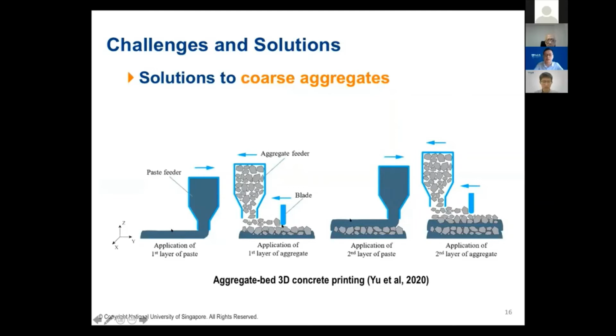Then we put another layer of cement paste. Then the cement paste could diffuse into the pores to fill all the voids in the aggregates. Then we put another layer of aggregate. Then we repeat this step and step. Then finally we can produce our concrete products. And later I will have one short video to show you the main steps.